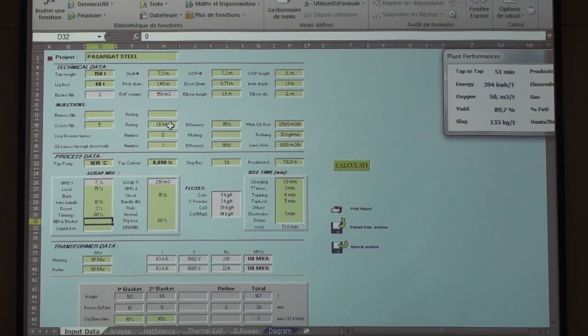Here you don't need high power, in case this was for DRI, but usually it's 3.5 megawatts. And per nozzle, it's not good to go higher than 2,500, otherwise you have splashes and stuff like that. So minimum is 1,000 cubic meter per hour, and maximum 2,500. Even 2,500 is quite high for oxygen, for the splashing.